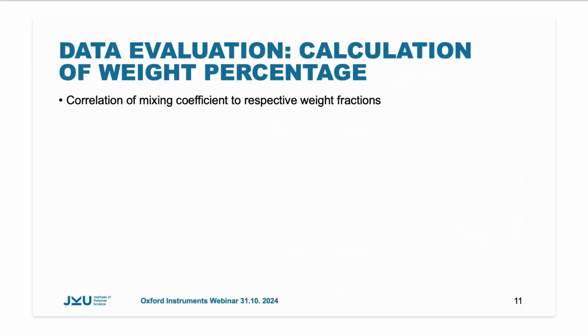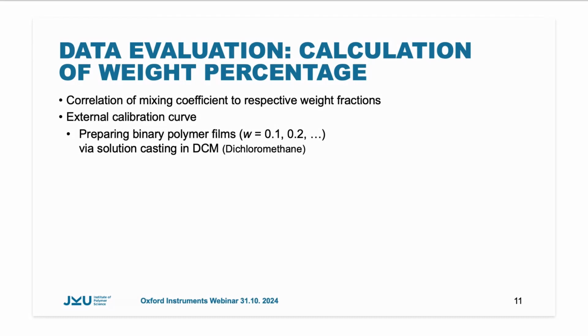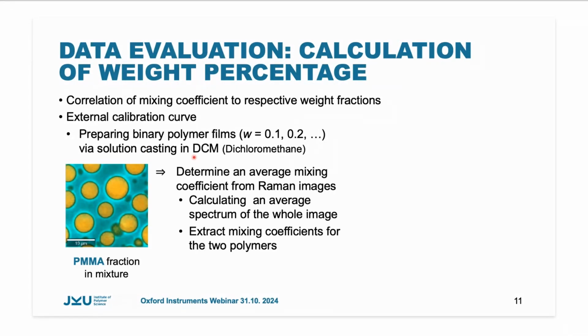Therefore, we have to correlate the mixing factors to the respective weight fractions, and we have to measure an external calibration curve. Therefore, we prepare binary polymer films with increasing amount of one of the components. We solvent cast them on a surface and then record a Raman image, similar to what I showed here. And then we can determine an average mixing factor coefficient from the Raman image, just calculating an average spectrum of the whole image,